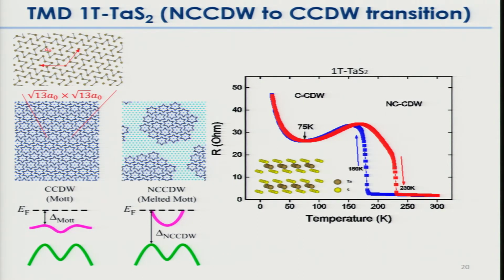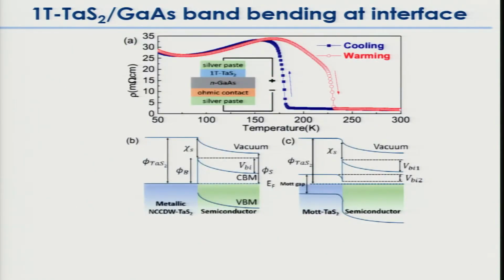These exist as isolated clusters, and there's a conducting medium between them. But when you cool down, it forms a really nice commensurate charge density wave with these, 13 atoms, constricted in towards a central atom. Each star is 13 atoms, okay? 12 outer atoms constricted in a little bit towards the center. So that's our Mott phase, and we're going to look quickly at the band structure. That's the resistance, just to remind you.